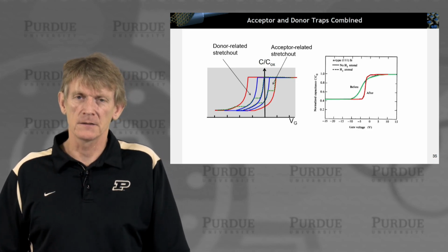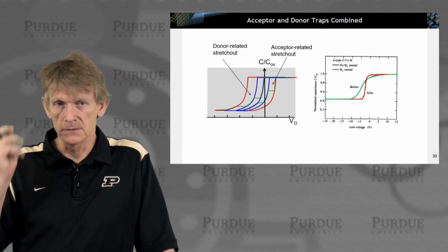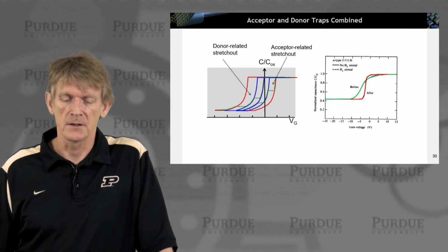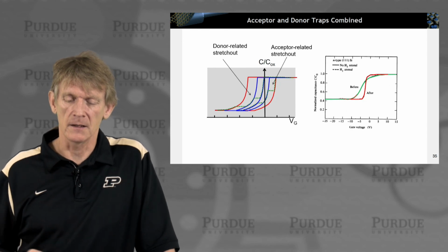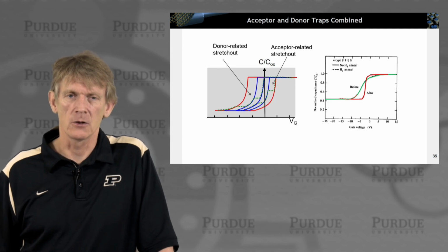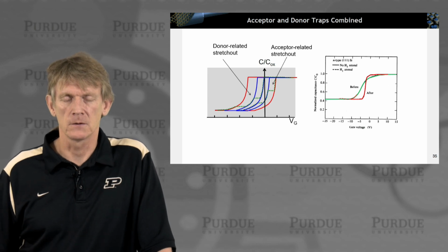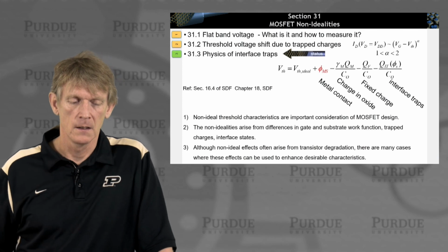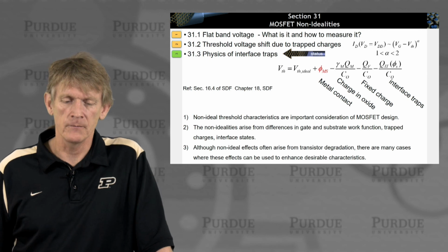And that is how you get to the case where if you have bad interface states, characteristics in your device, and you haven't annealed, you have a CV curve that's stretched out like this, and after the anneal, it becomes more like a CV curve that you would expect in an ideal sense, where you don't have significant numbers of interface traps anymore.